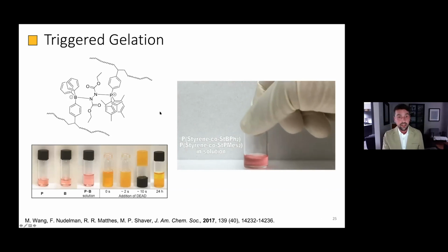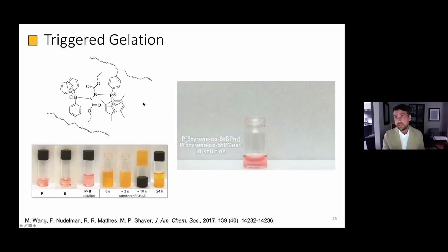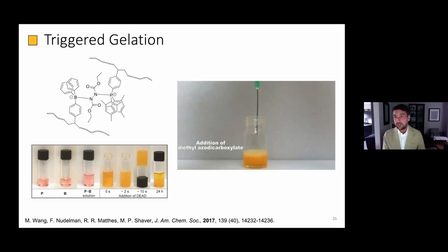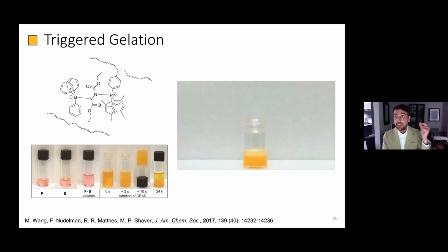It is for me. So if I take those two things and they're in solution, nothing is going on. I've got no change. I add my diethyl azodicarboxylate, which is just a surrogate small molecule we're adding in because it gives us good reactivity. And almost immediately I have a transformation. And this sets very, very quickly just with that small molecule addition. In about 10 seconds, you can turn this over, but Meng, the PhD student and now postdoc who's working on this project, is taking his time to put the syringe waste safely, and he'll come back in and flip that vial over in a second.